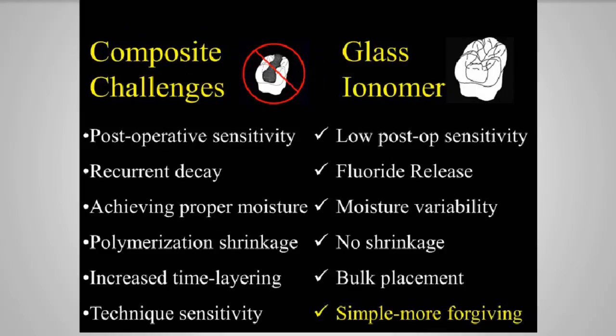The challenges that we see with composites can be taken care of more easily and more routinely with glass ionomer. The postoperative sensitivity that we talked about due to improper use of bonding agents, you just don't see that with glass ionomer. Recurrent decay is the number one reason for replacing composites. You don't have to worry about that because you've got the fluoride release. It's so important to get the right moisture, like we mentioned earlier. Glass ionomer is much more forgiving.